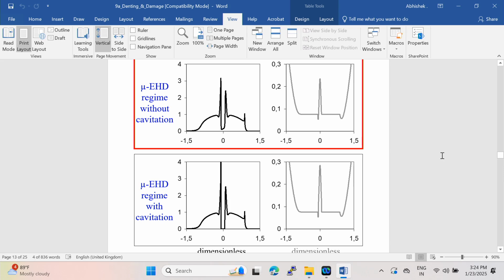Now, these are two other situations. Now the dent is deeper. Then, when it is deformed, you can still see the cavity. Okay? And there is also some peak of pressure which is due to the EHL lubrication. On the left, you can see that the minimum pressure is not nil, which means that there is no cavitation.